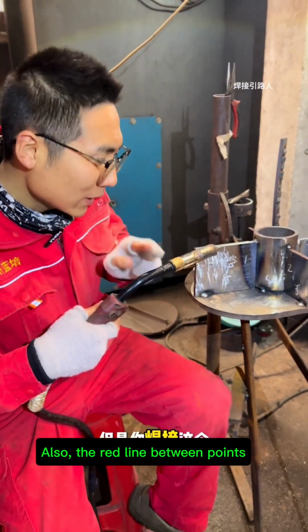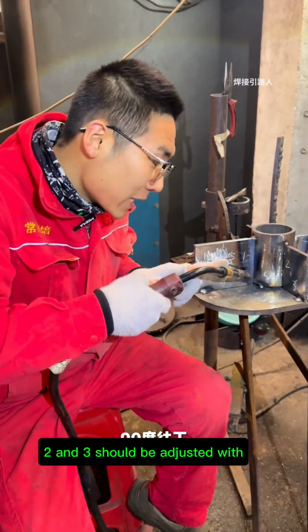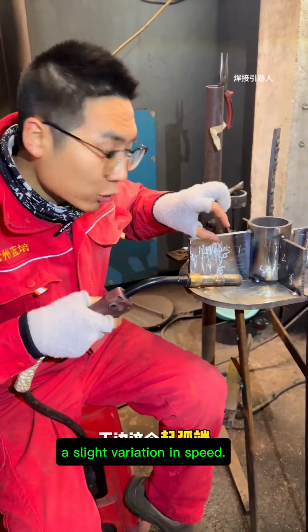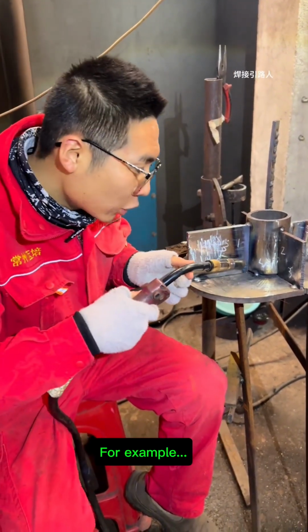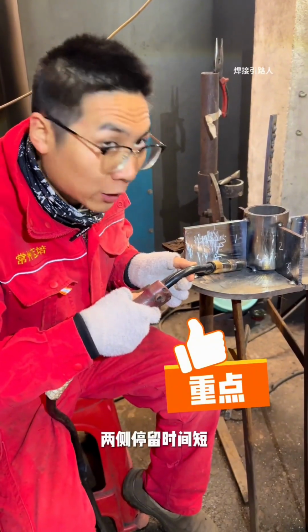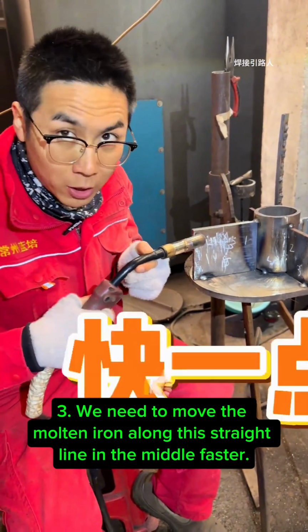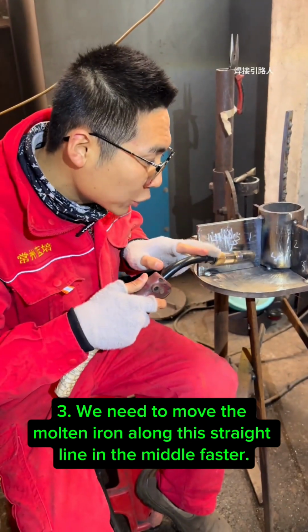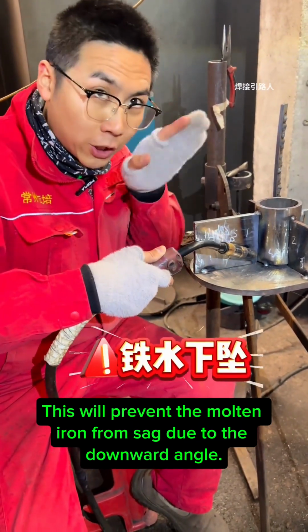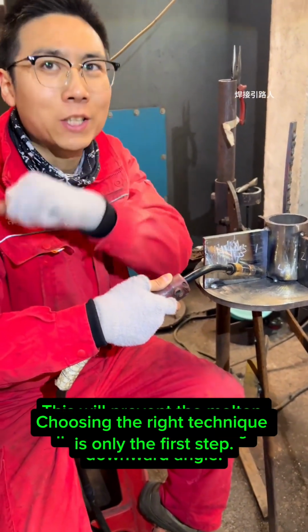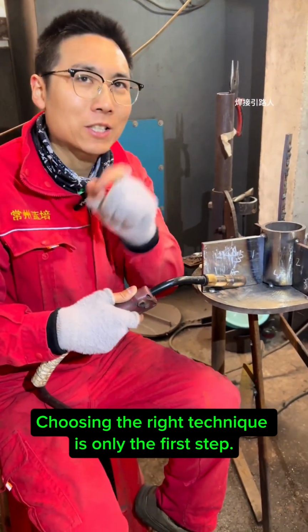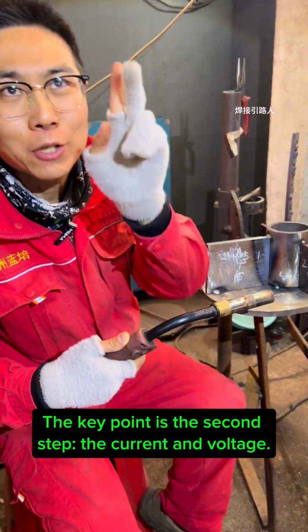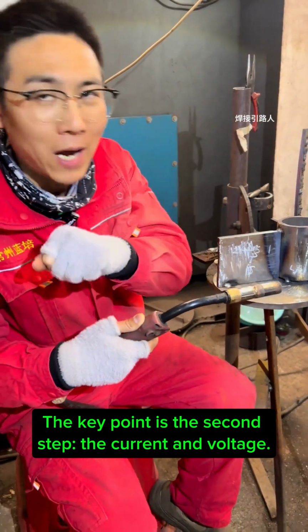Also, the red line between points 2 and 3 should be adjusted with a slight variation in speed. For example, we need to move the molten iron along this straight line in the middle faster. This will prevent the molten iron from sagging due to the downward angle. Choosing the right technique is only the first step. The key point is the second step, the current and voltage.